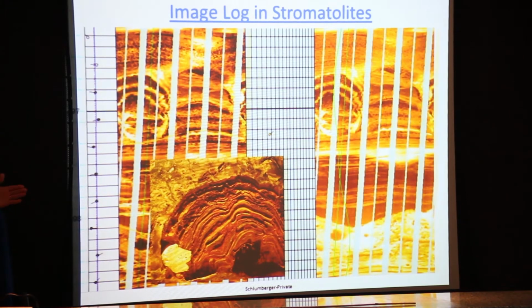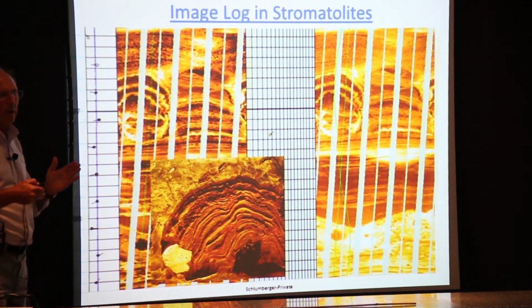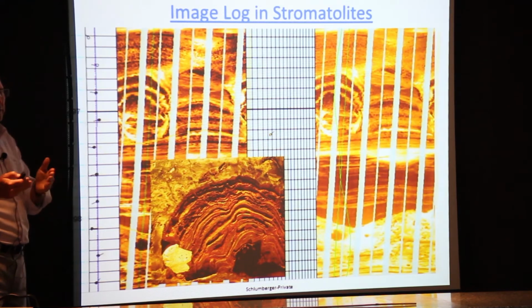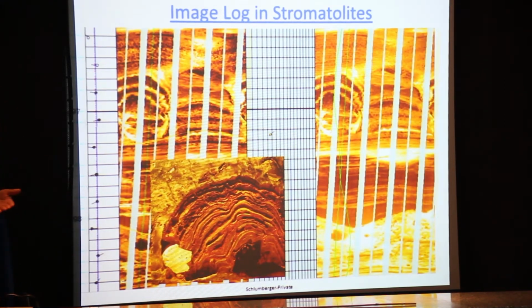So most of these pre-salt wells that have not produced oil have been because you've had precipitation of other minerals as the hot hydrothermal fluids move away, they cool down, and you lose porosity. So there you're losing porosity due to precipitation, not so much compaction from the overburden.